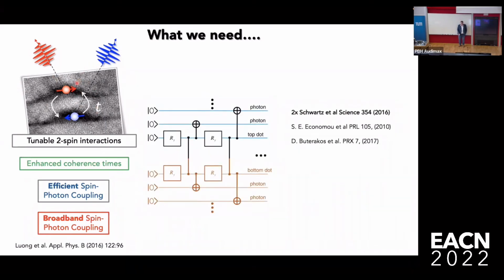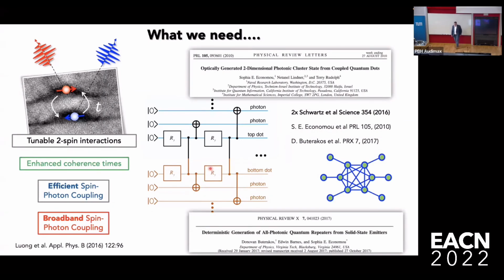Incidentally, this is nothing more than, let's say, twice the protocol for the cluster state generation that we just looked at a couple of minutes ago. So this is an example of, that's the Schwarz paper here. There were predictions already 10 years ago from Sophia Economou for doing this with 2 spins, and by doing this, generating then 2D cluster states deterministically, which are then useful for quantum repeater architectures. So you need to either take linear cluster states and fuse them together to make a 2D cluster, or you can directly generate a 2D cluster state using 2 spins in this way.